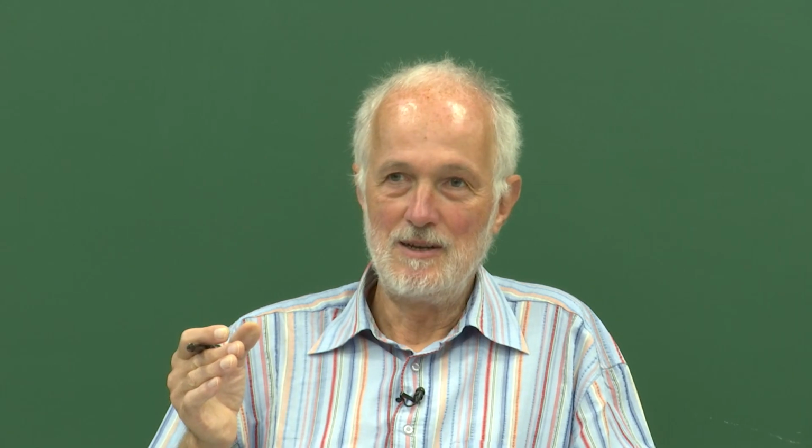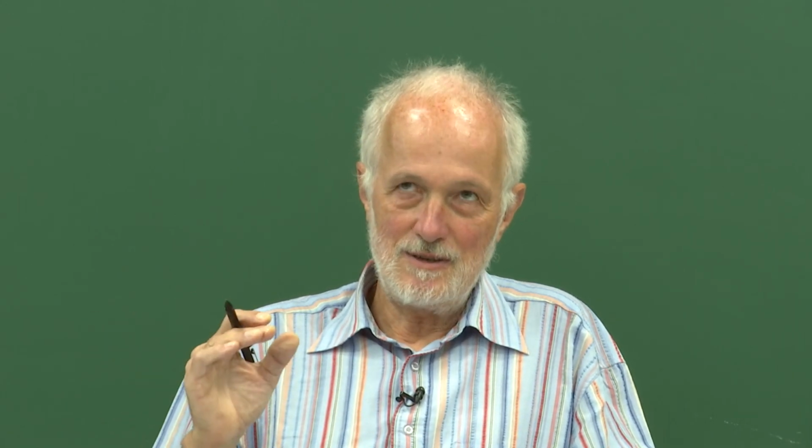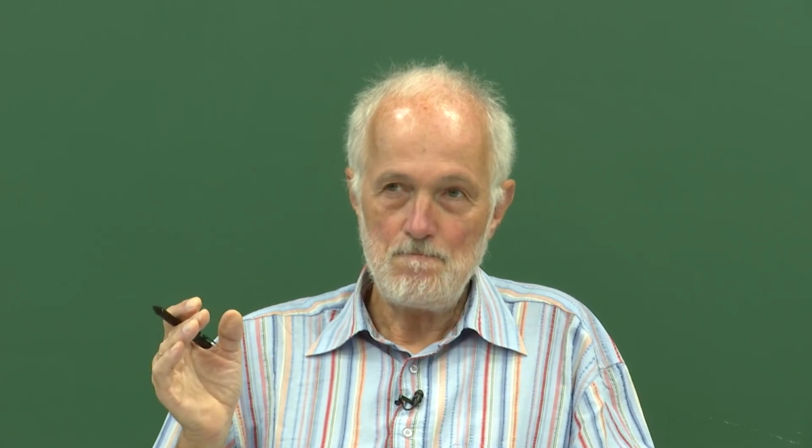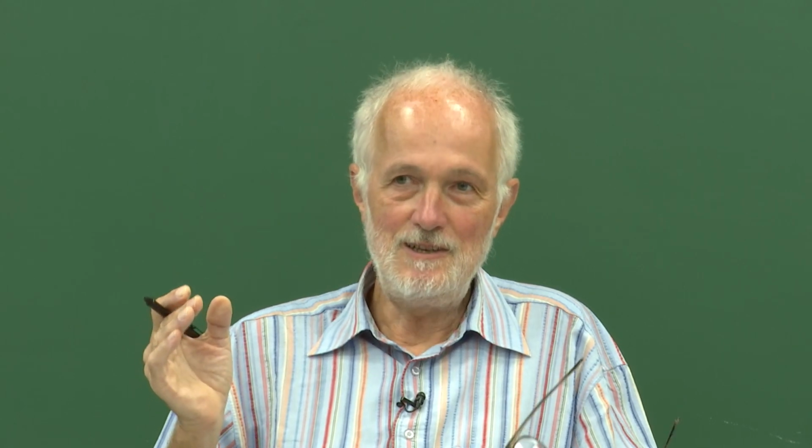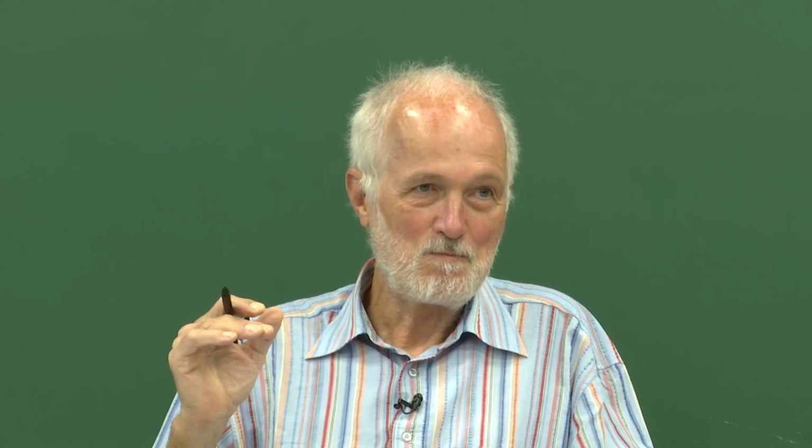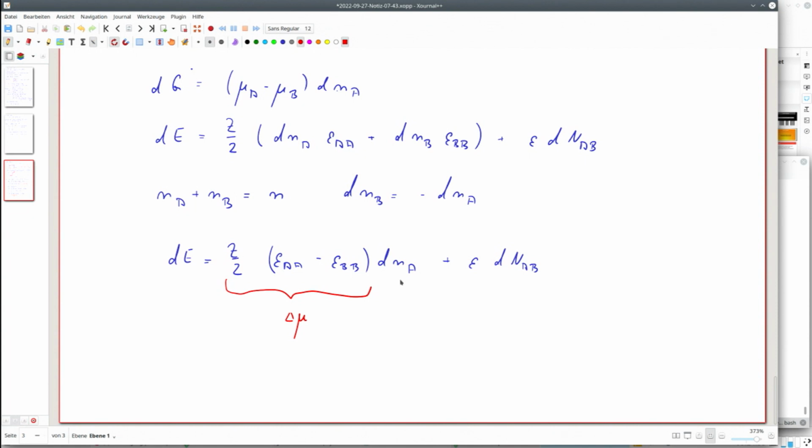If you want to make a B out of A, this means that dNA is -1. Vice versa, it's a +1. So you add or subtract this term to the total energy for either of these possibilities. In principle, it's very simple and very fast, and the concentration then adjusts according to the value you gave here.